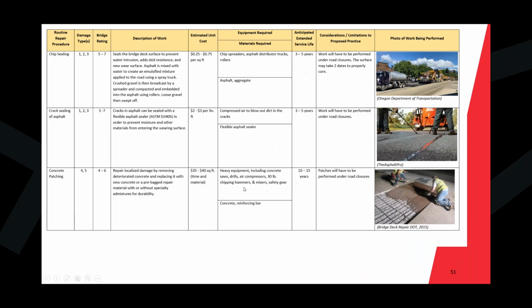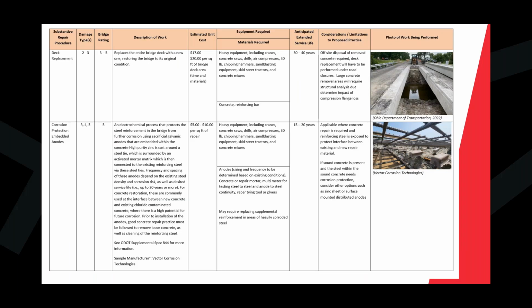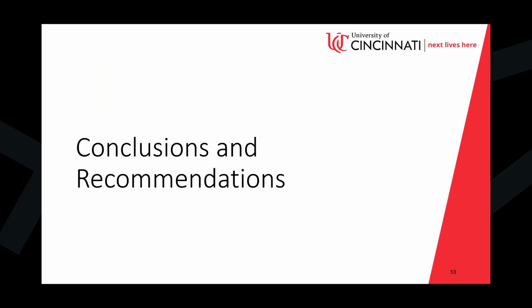This is just showing you routine repair procedures, just a few. So examples like chip sealing, crack sealing of asphalt, concrete patching. And then more substantive: replacing the deck, or you need to remove a lot of concrete and you decide to use embedded anodes, a form of cathodic protection that we did not use on this project. Okay, and so this is the matrix that we developed that includes these different kinds of information, again, to try to be somewhat comprehensive in terms of the options that you have for dealing with this corrosion issue on box beam girders.